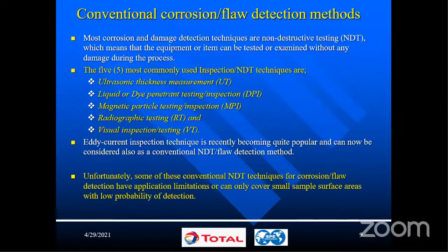In the dye penetrant methodology, we are looking for mainly cracks or porosities where you apply a dye on the surface of the metal to be tested. And due to capillary effect, the dye is sucked into the porosity or the cracks. And with the developer, you're able to bring it out and it gives you a visual image of the defect on the surface. Similar to the magnetic particle inspection, a magnetic dipole is applied across the area you want to test, and magnetic filings dissolved in a solution is applied, and then they get attracted to the magnetic poles that are created by the defect. Radiographic testing is clear.